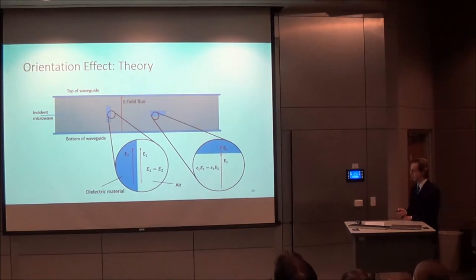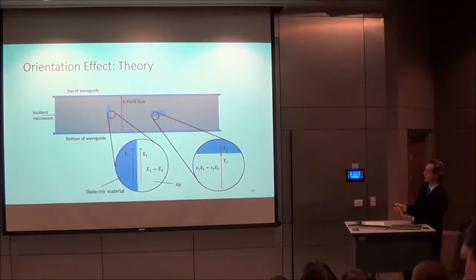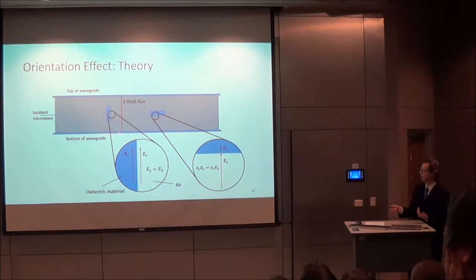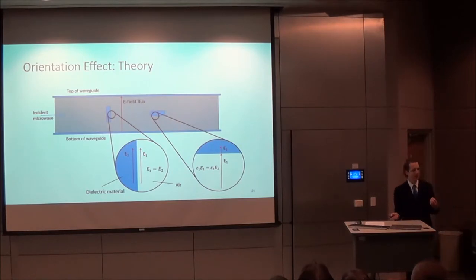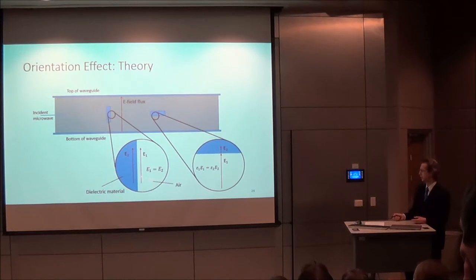And briefly, the theory behind this can be illustrated with this diagram. So here's the waveguide, a cross section of it, and this is the top, the bottom. The electric field lines are going from the bottom to the top and the top to the bottom, vertically situated. And so as the incident microwave meets the material, the electric field produced is going to be equal directly outside the target and directly inside, where the electric field flux lines are tangent to the dielectric interface. Air is a dielectric as well, so this is a dielectric interface.